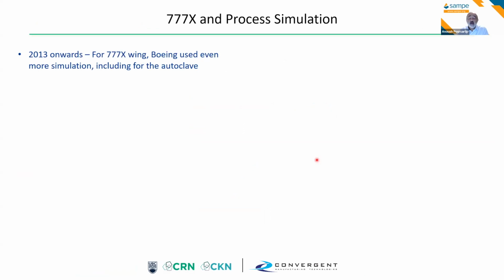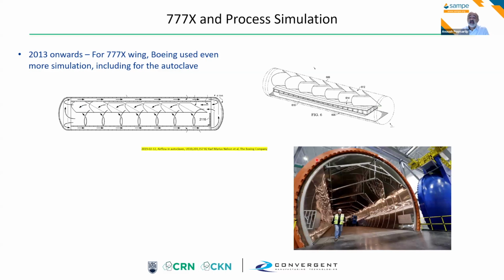Boeing actually extended that when the 777X program was launched. Boeing went a step further, and they said, can we actually use simulation not just for the part, but for the autoclave? And by coupling computational fluid dynamics with that kind of thermochemical simulation, they were able to design a very sophisticated longitudinal flow autoclave, which was then, of course, patented.